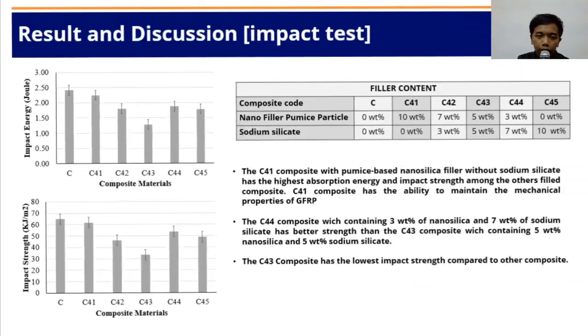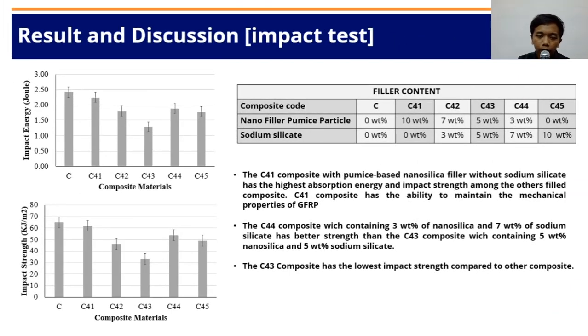Then the next slide is the result and discussion about the impact test. The chart shown below is the result of Izod impact testing on GFRP composite. As we can see, from the scope of filled samples, the C41 composite, which is only filled with pumice-based nanosilica filler without sodium silicate filler, has the highest absorption energy and impact strength among the others.